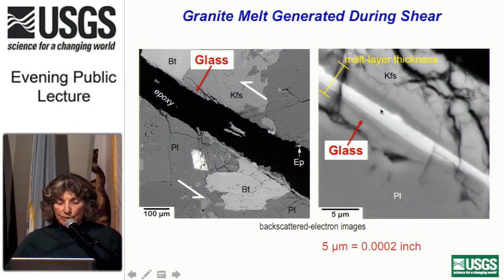And then you get the progressively darker bands here. A spot analysis with the EDS system of some of this dark material shows that it's a mix of the two feldspars that are in the rock, the potassium feldspar and the plagioclase. And it also contains a certain amount of quartz in it.